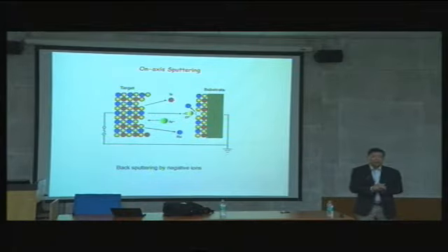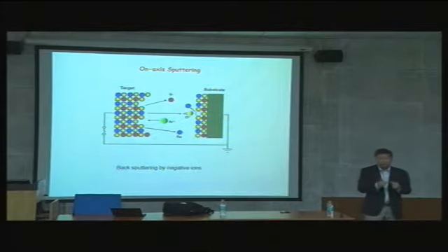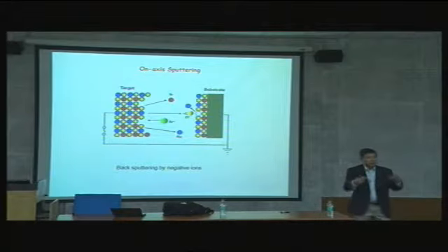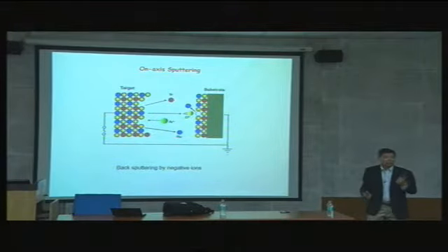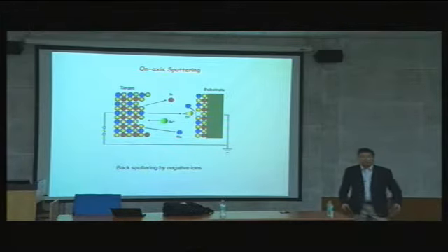But in that region the mean free path is short, but not very short. It's still long. So the oxygen coming out is scattered by the argon gas molecules, but not strongly enough. It still arrives here as a very high energy particle. So one simple approach people use: why don't you put tons of gas in it? You put in like 400 millitorr. That's 300 to 400.